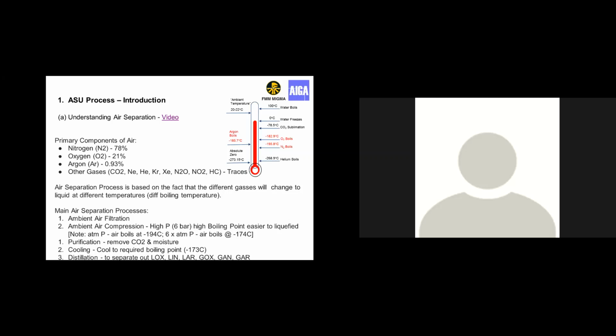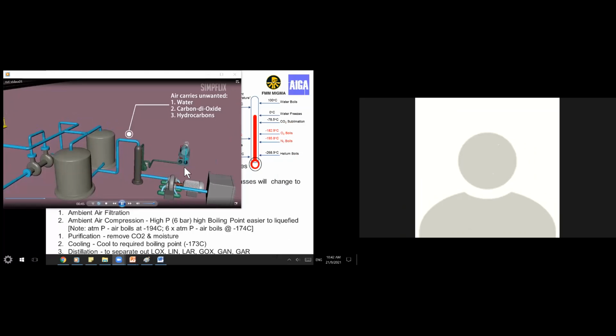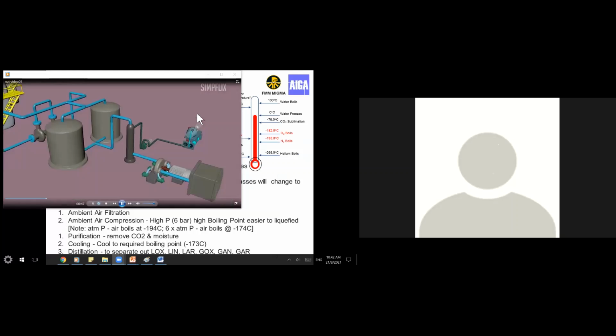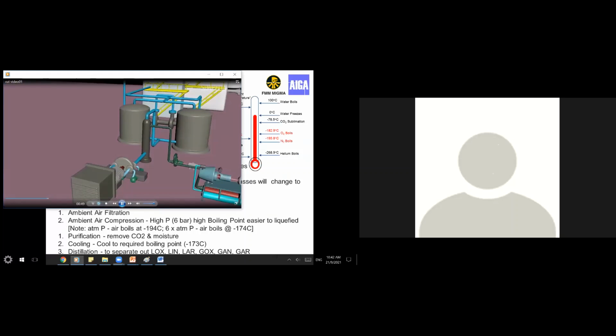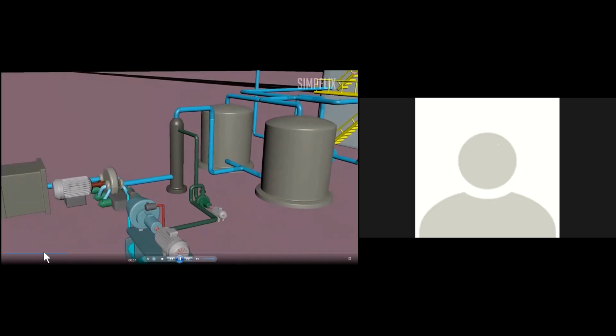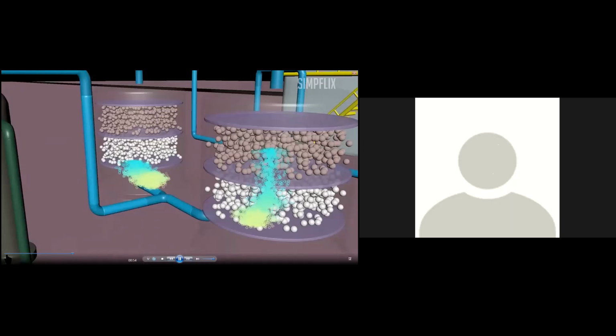At high temperature, the air is cooled in the pre-cooling system to around 10 degrees Celsius using refrigerated water. During this cooling process, impurities like carbon dioxide, which are not required for us, are present. Water, hydrocarbons, and carbon dioxide are removed in the purification units using molecular sieves and activated alumina.